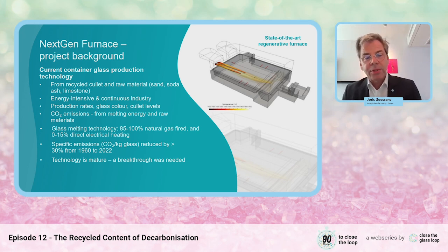And this glass melting technology, the furnace you see, is mainly fired by gas heating. So let's say at least 85% till 100%. And sometimes it's added by boosting, as we call it. These are the little red pins you see sticking into the furnace, which add additional heating capacity, and that's electrical. The specific emissions of these furnaces have been worked on since decades. This type of furnace is already 150 years old.